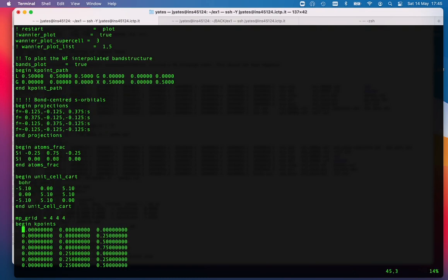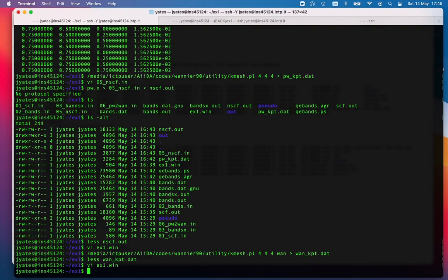And pop them all in. So in order to construct the Wannier functions, as we discussed earlier, I'm going to need the M matrix and the A matrix, so the overlap matrix and the projection matrix. So we need to be able to tell the plane wave code what it is that we need to compute. So to do that, we first run Wannier90 in what we would call pre-processing mode.